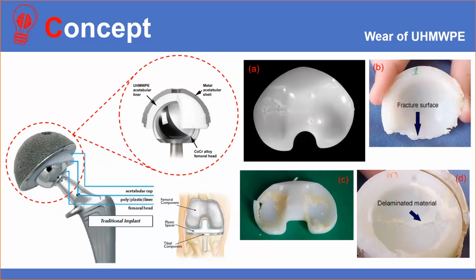Macroscopic evidence for the oxidative degradation caused by gamma sterilization in air can be seen in figure A, where it looks like a white halo and is called the crown effect or white band. This is a zone where a critical molecular mass decrease has occurred and which therefore has very low mechanical properties, resulting in the well-known effect of delamination and fracture that is typical of such components. Figure B and figure C show the fracture surface, and figure D shows the delamination on the inside surface which occurred over time. Okay.